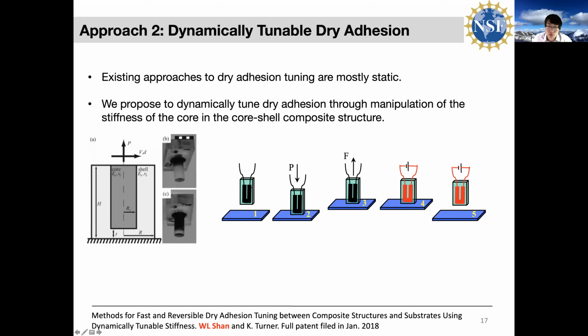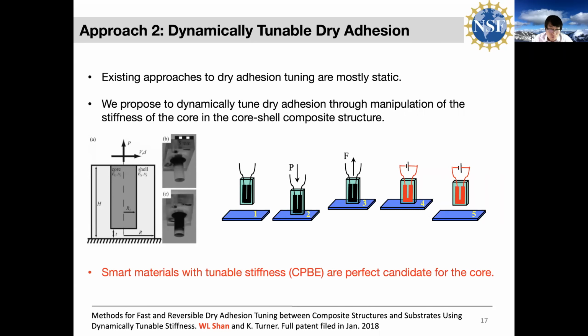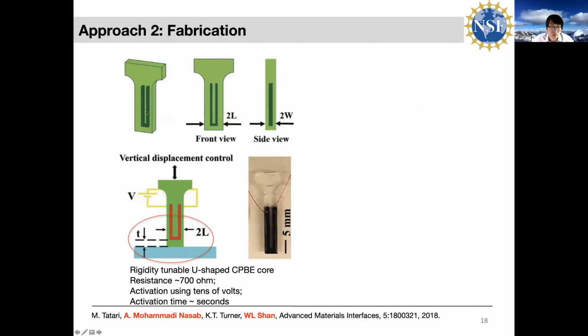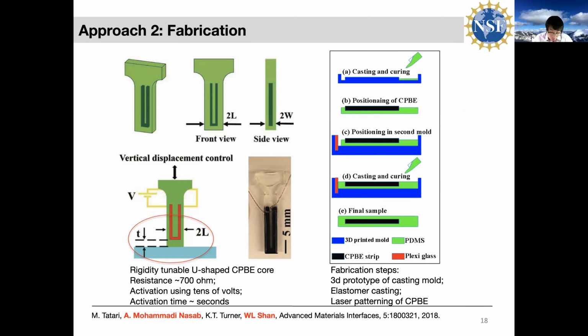So when we have a rigid core, it will have high adhesion. When we activate the core to soften it, we will have lower adhesion, and that way we can pick the object up when it's rigid, and then do the manipulation and release when needed by just turning the switch. So smart materials with tunable stiffness, like CPBE, as we described earlier, are perfect candidates for the core here. We went on to implement the design, and instead of those circular shapes, here we have a rectangular cross section. This is more for convenience of fabrication. Here there's a fabrication step, which I'm going to skip the details of.